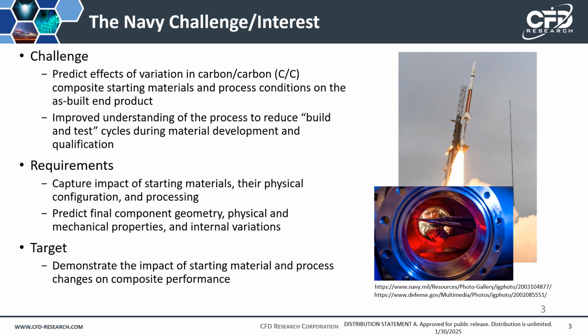Modeling this slow process can potentially allow us to predict the outcome much faster than experiments alone and provide insight into how the composite structure develops during processing, thereby reducing the number of these very slow material build and test cycles during material development. One of the Navy interests is capturing the impact of variability in the starting resin and woven fiber materials, particularly if suppliers change. Details of the process itself, such as the pressures and temperature histories used in each cycle, will also affect the quality of the final product.